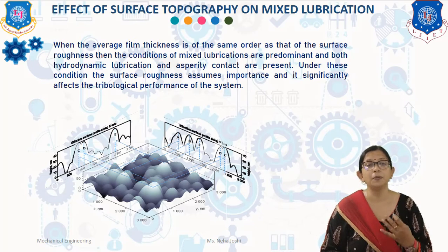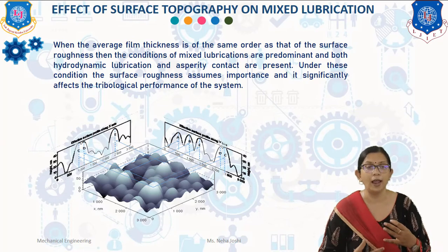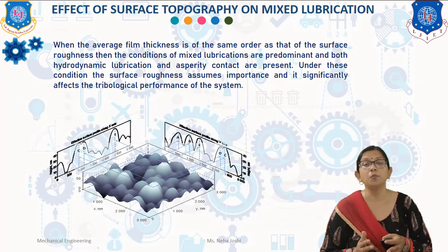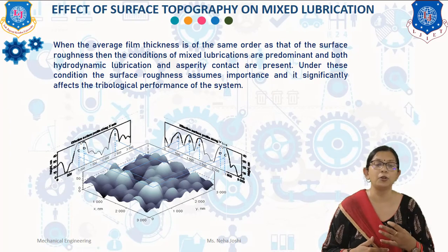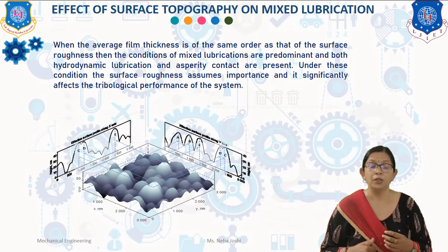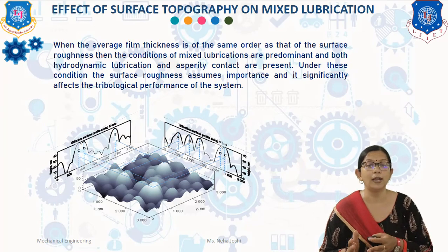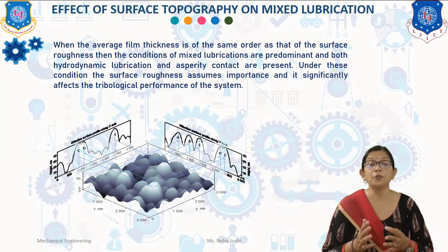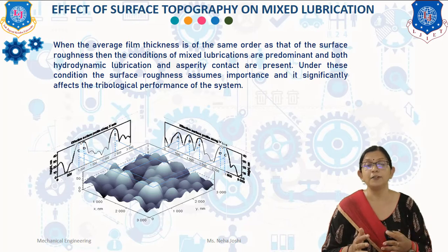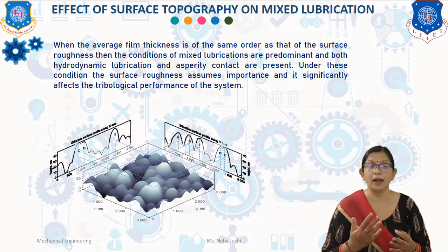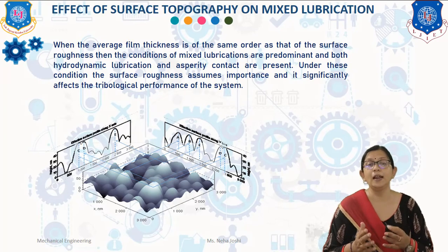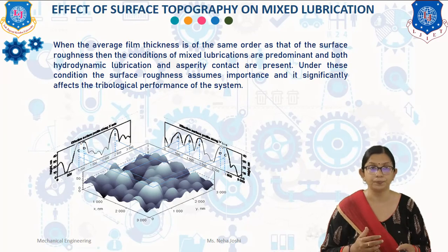Since the surfaces produced by manufacturing processes have non-Gaussian height distribution, skewness and kurtosis, which define the non-Gaussian height distribution, will in general be the most influencing parameters with respect to tribological performance. Okay, so it has been observed that surfaces produced by single point cutting tools, like shaping and turning processes, generate positively skewed surfaces. While surfaces produced by multiple cutting tools, like grinding, honing, etc., generate negatively skewed surfaces and in addition have a kurtosis value.